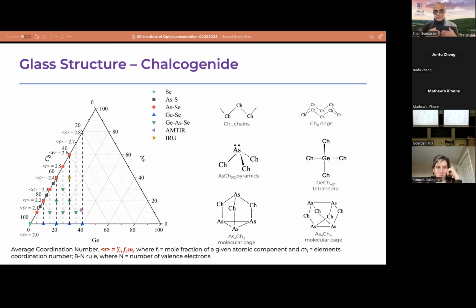One way to differentiate and also define the glass is to come up with an average coordination number we call R. What we do is take the mole fraction of every atomic element in the glass composition and its coordination number, sum them all up together, and come up with an average coordination number. That's the R number. That's important to see. There's a range of R numbers you will get for all these compositions. For example, 100% selenium has an average coordination number of 2. We use the 8 minus N rule, where N is the number of valence electrons in the element. For selenium, it's 6. So 8 minus 6 is 2. So the coordination number we can expect for selenium is 2. This is one way of bookkeeping for us to keep track of which elements are getting coordinated in my piece of glass.